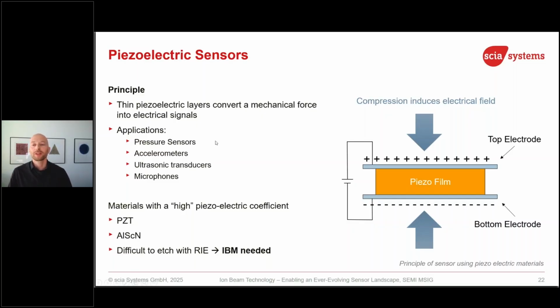So those piezoelectric effects are used, for example, for pressure sensors, accelerometers, ultrasonic transducers, or microphones. The materials which are common are PZT, with a very high piezoelectric coefficient, or aluminum nitride or aluminum scandium nitride, because PZT, you cannot use it in CMOS fabs. So for those customers sensitive to certain materials, aluminum nitride is a material of choice. And the PZT, and especially the highly doped scandium aluminum nitride, are difficult to etch with RIE.